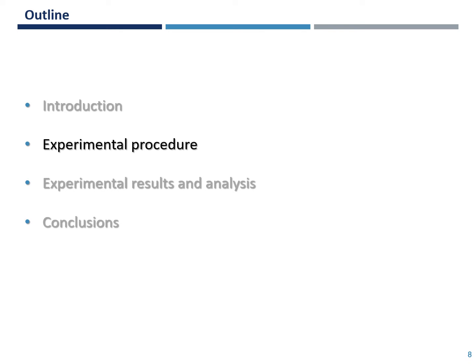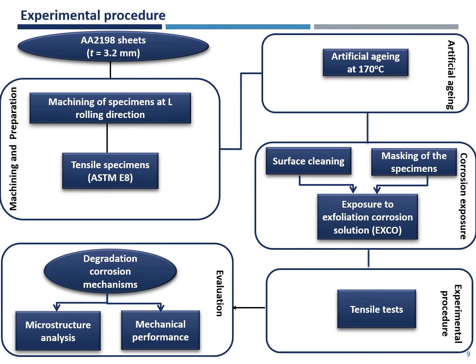Moving on to the experimental procedure. Firstly, tensile specimens were machined from the sheets of aluminum alloy 2198 parallel to the rolling direction. Afterwards, the specimens were exposed to artificial aging heat treatment at 170 degrees Celsius. Then the specimens were surface cleaned and exposed to exfoliation corrosion solution. Later, the tensile tests were conducted, and finally the evaluation was done through microstructural analysis and mechanical performance.